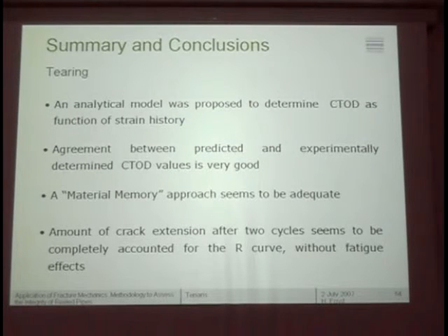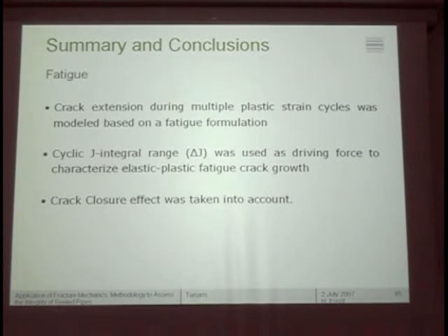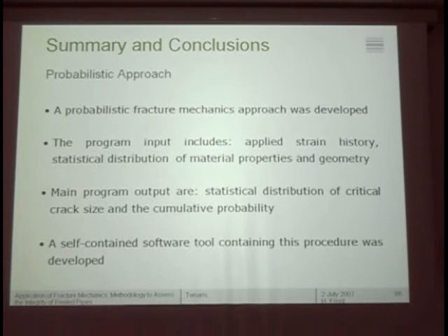Well, in summary, for tearing, an analytical model was proposed to determine CTOD as a function of strain history. The agreement is reasonably good. The material memory seems to be adequate for the resistance curve. The amount of crack extension after 2 cycles seems to be completely accounted for by the resistance curve without fatigue effect. If we put more cycles, of course, crack extension during multiple cycles was modeled based on a fatigue formulation. Delta J was used, or delta J effective, and the crack closure was taken into account.